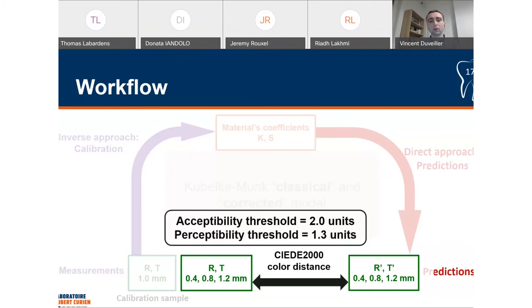For this color space, researchers of the dental field have carried several studies which show that a prediction is acceptable if the color distance between the prediction and the measurement is below 2 units, and that the perceptibility threshold is around 1.3 units. So this will be our goal for this experiment. Now let me show you the results.